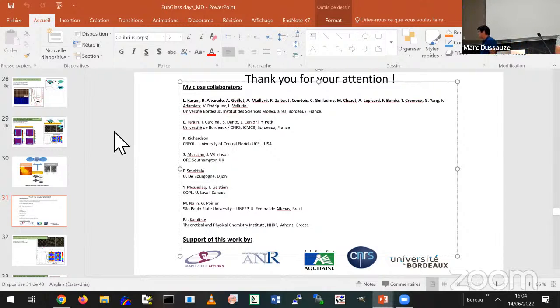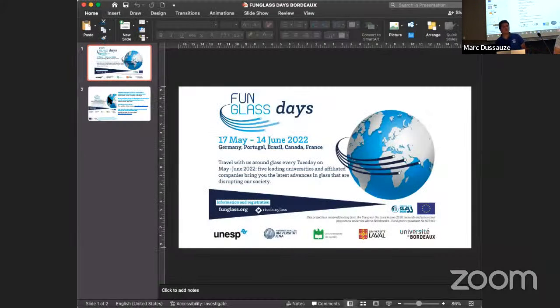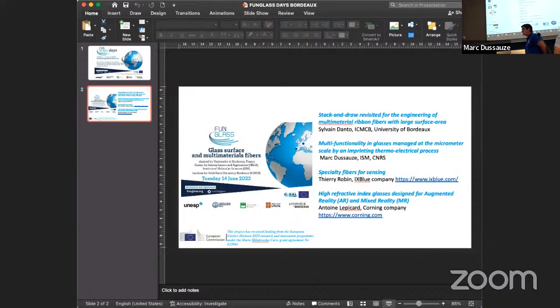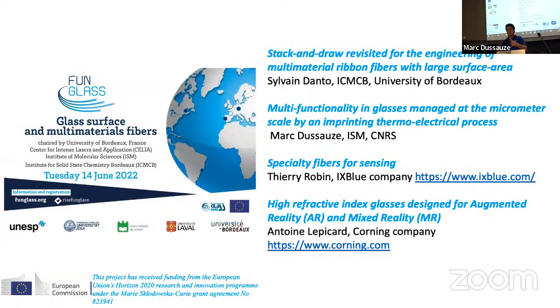Maybe there is a question on the chat. Yes, you're right. So there is a question: what is the resolution of the patterning? For the first part of the talk, the resolution can be down to 1 micron. But for the liquid crystals, I don't know. The best we have done, because for the liquid crystals you really need this plasma, and you cannot work with very tiny electrodes, is some squares of 40 microns of size. But the important point is that you need enough glass. So if you work with thin films, it's not enough. But if you have a few microns of glass, it's good. So for the liquid crystals, I hope we can go below 10, but we have to try.